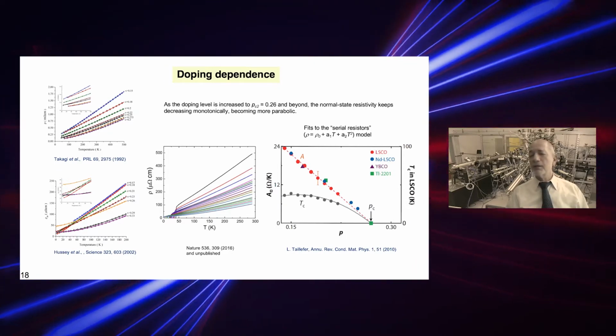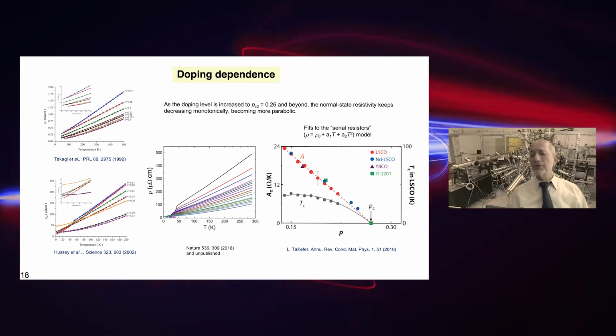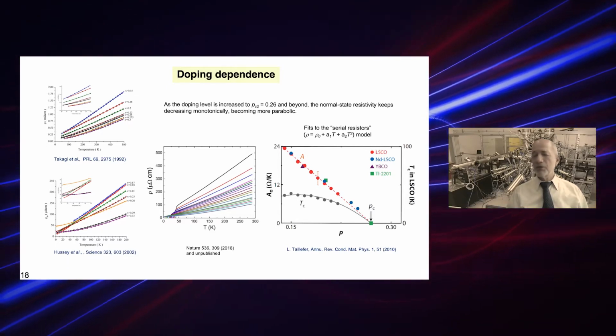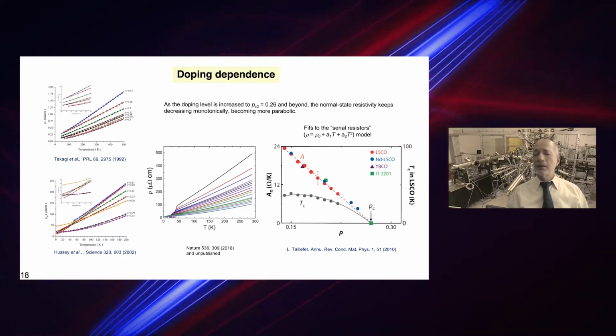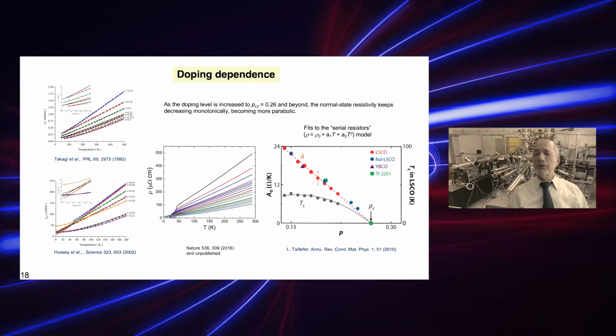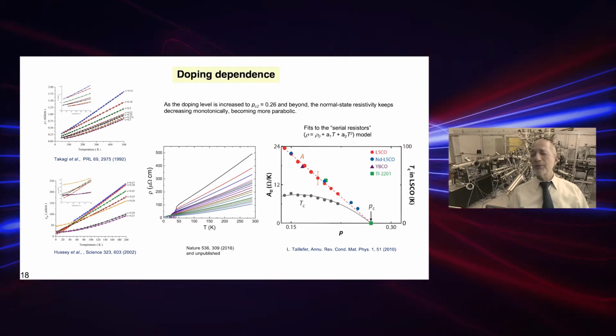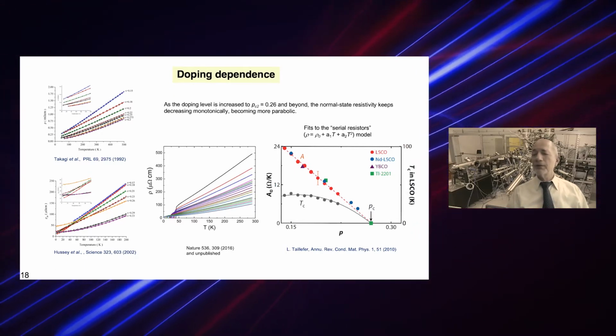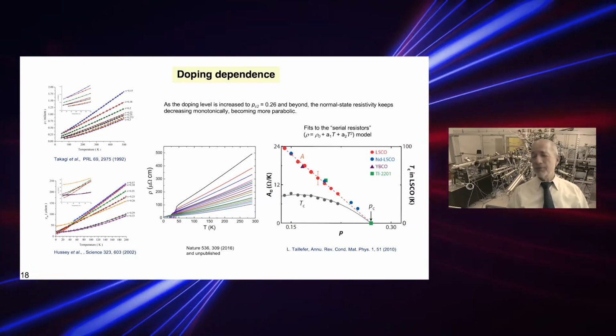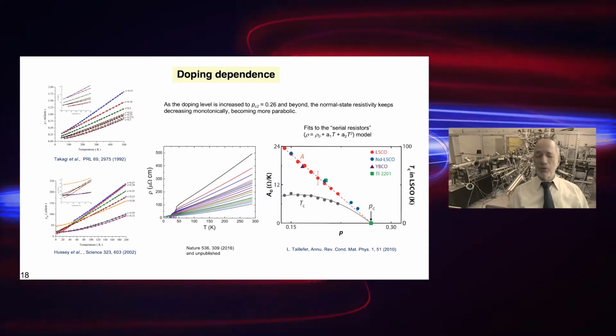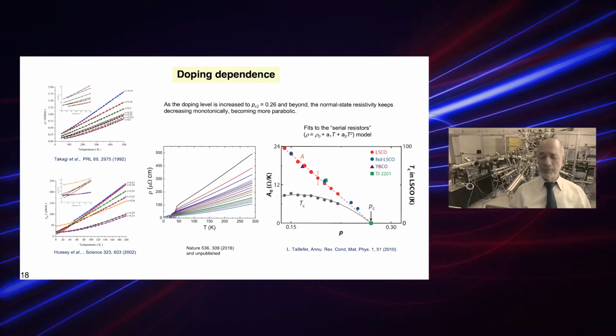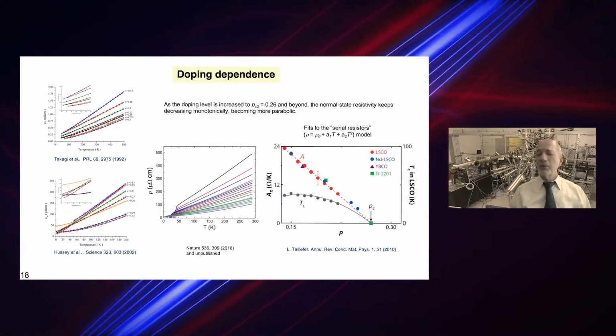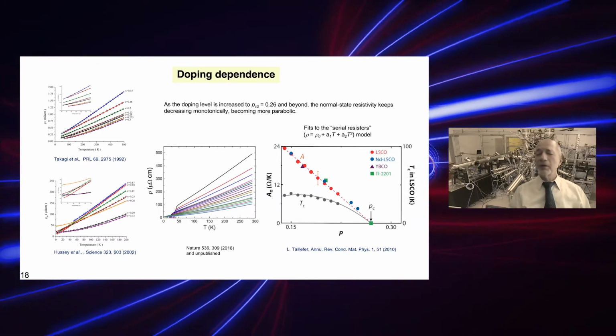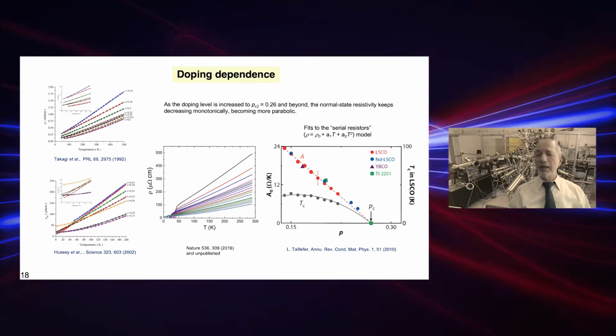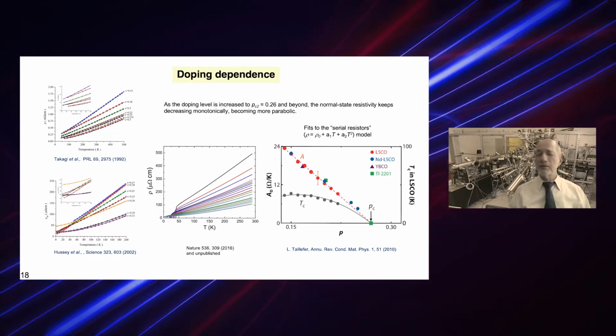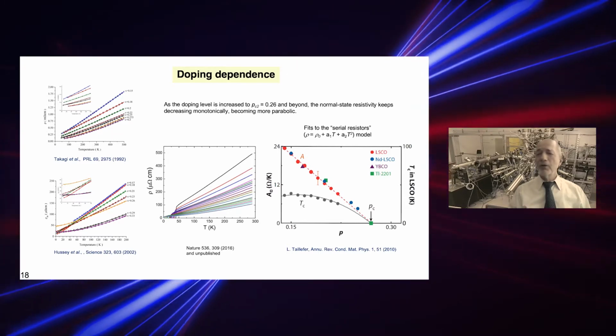The one that is shown here is selected so that this straight line is a perfect tangent, but if I change the scale, I could make it horizontal or vertical. The other problem is that some of these dots were from YBCO and thallium, and those actually have different domes from lanthanum strontium cuprates. But these caveats aside, what you can take home is that the linear contribution, the strange metal contribution, is actually decreasing as you go more and more overdoped.